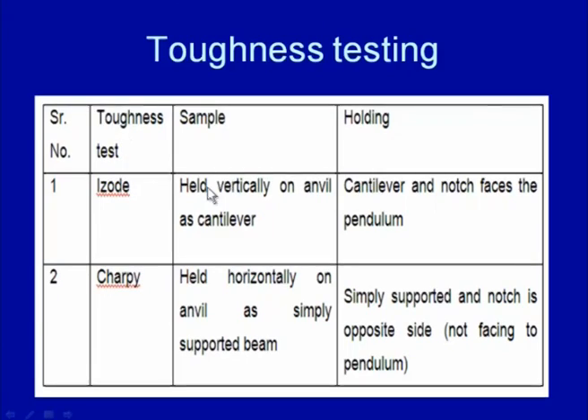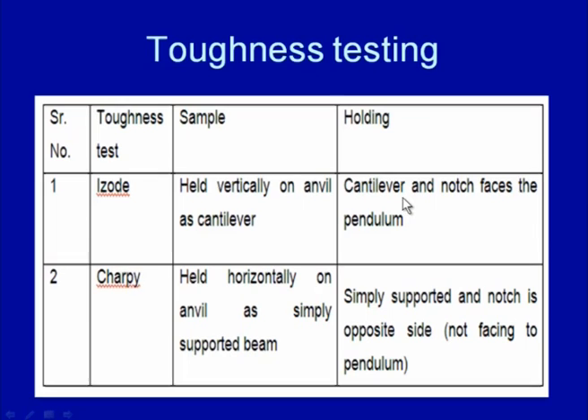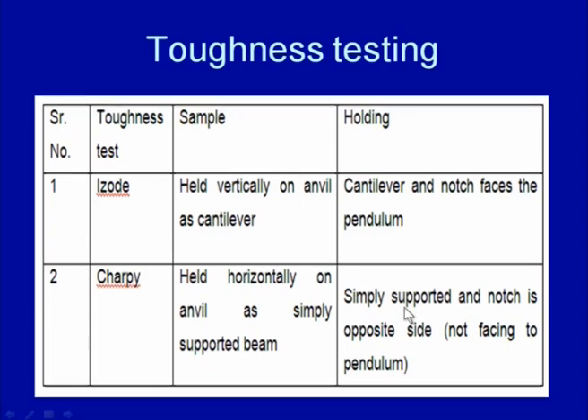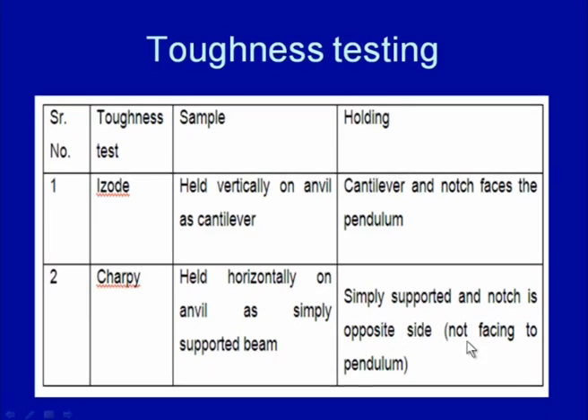In the Izod test, the specimen is held vertically in a cantilever manner, while in the Charpy test, the specimen is held horizontally on the anvil as a simply supported beam. In the Izod test, the notch faces the pendulum when it hits the surface, while in the Charpy test the pendulum hits the specimen from the back side of the notch and not from the facing side. This is the difference between these two methods.